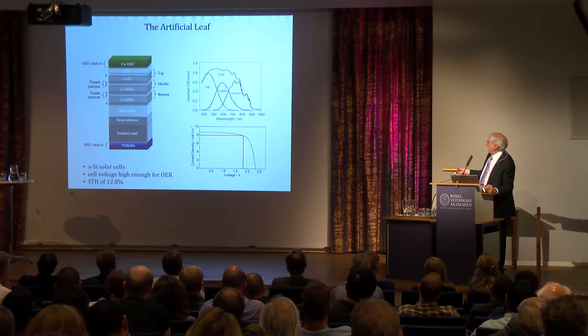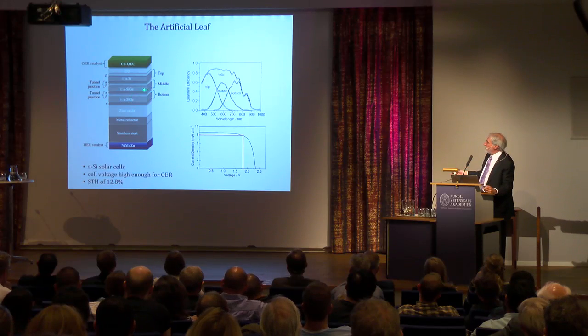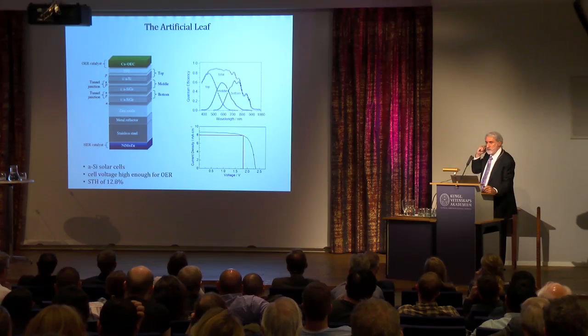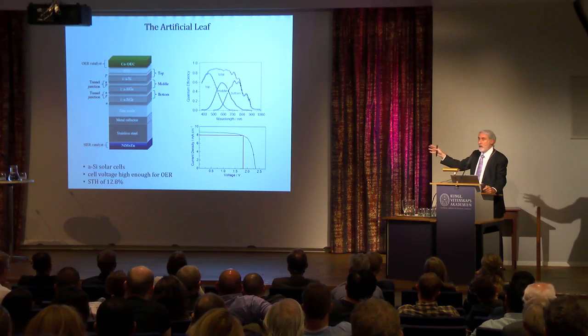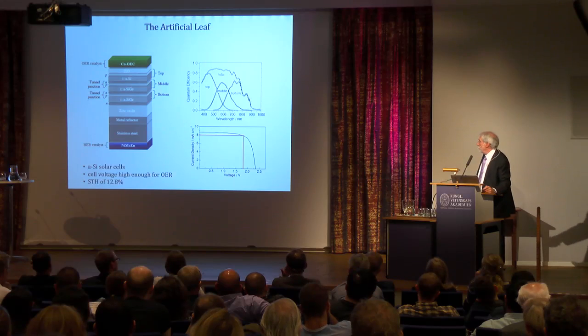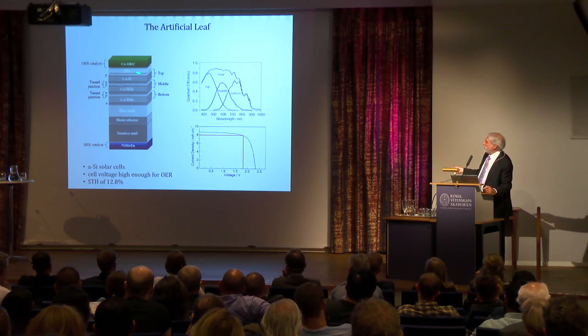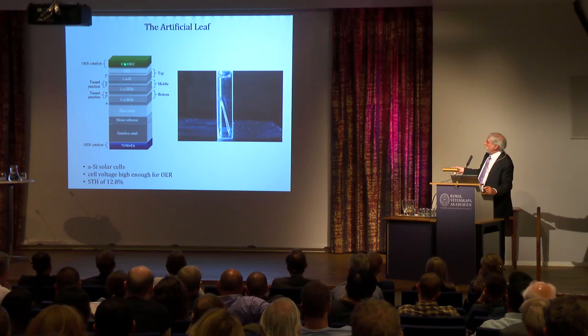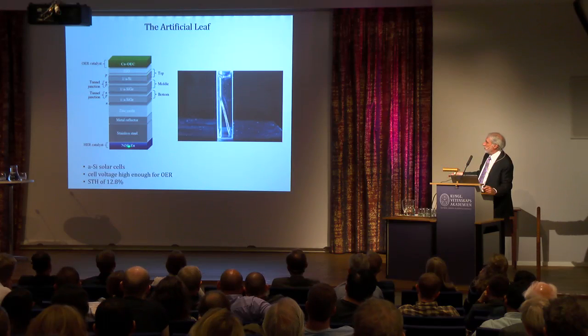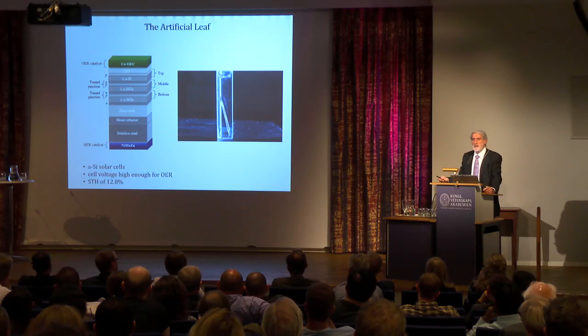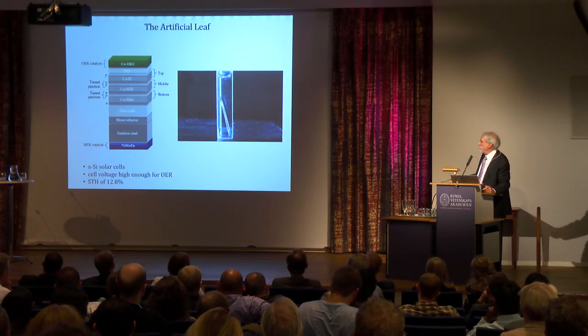And then it turns out, this is 0.5 plus 0.5 plus 0.5, so you get around 1.5 volts of voltage. So I have plenty of voltage now. I don't need to put any external input in. And now I coat my catalyst here. And so I talked to you about this catalyst. This is the cobalt catalyst that makes oxygen. We made a nickel molybdenum zinc alloy, a thin metal alloy, which collects the electrons to make hydrogen.